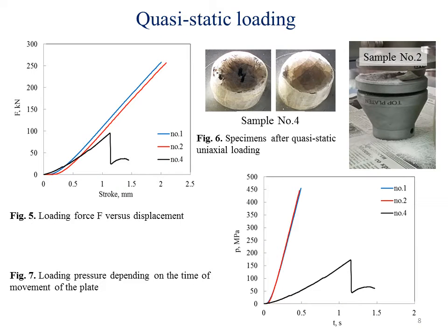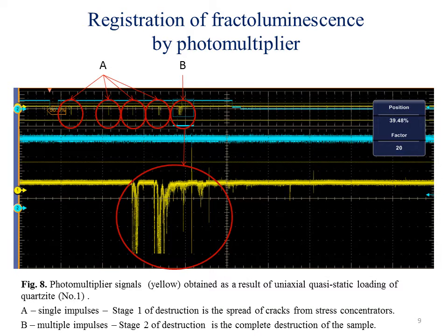In the interface of the loading machine, data was recorded on the dependence of the loading force on the plate movement, as shown in figure 5. For example, for the fourth sample, the first part of the signal corresponds to the formation of cracks in the sample, at which the sample has not yet collapsed. The second corresponds to additional loading and complete destruction, as shown in the photo for sample 2.